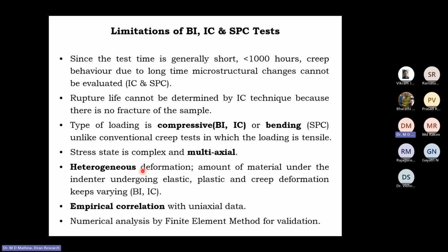I must also point out the limitations, which I have been listing out one after another during the course of this presentation. One is that since the test time is generally short, often much less than 1000 hours, the creep behavior due to long-term microstructural changes cannot be captured. Secondly, rupture life cannot be determined by the impression creep technique because there is no fracture occurring. The type of loading is compressive in ball indentation and impression creep, and predominantly bending in the case of small punch creep, unlike conventional creep tests or conventional tensile tests, which are carried out under tensile loading conditions. Again, it is not monotonic, uniaxial loading. Here it is complex and multi-axial.